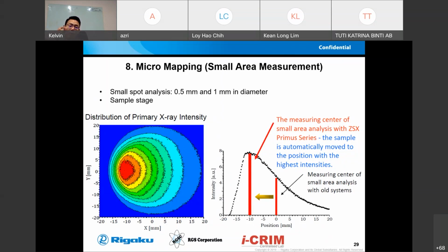Another important thing to bear in mind: if your sample is very small and you're using a very small spot to measure the point, in order to get a very good result you will need to lengthen the measurement time. For example, if you're measuring with the 30 millimeter spot, it takes about 10 minutes to complete the full scanning of all the elements. In micro mapping, you might need to increase it to maybe 30 or 40 minutes, depending on how many elements you want to measure.